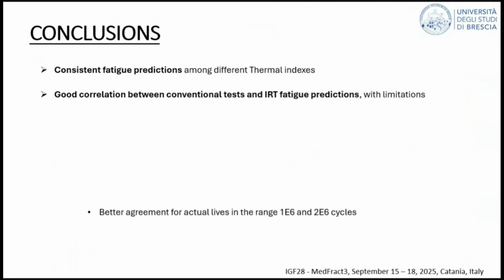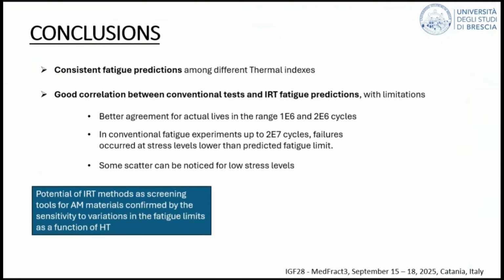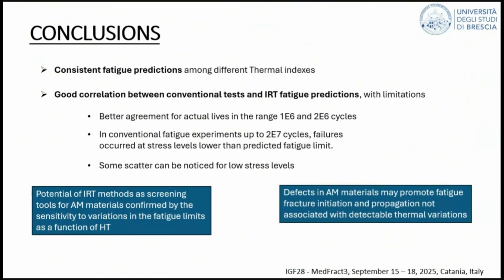And just to conclude my presentation, my basic message is, on one hand, we have found that infrared thermography can be a valuable tool for fast screening among different conditions of material. For example, you vary the parameters and you want to have a quick assessment of which could be the most favorable condition. On the other hand, we are facing some limitations that we think are related to the presence of defects in the additive manufacturing materials, so that the prediction, especially for high cycle number, is not perfectly good.